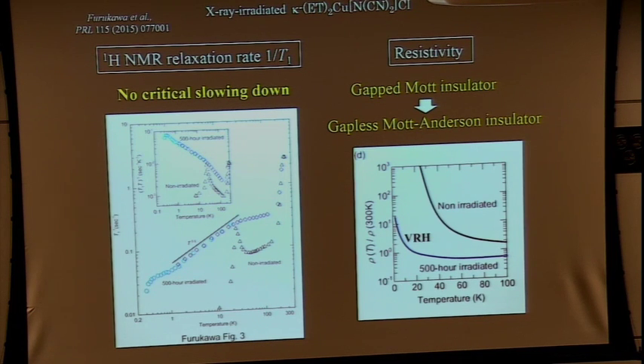However, we have to pay attention to the charge degrees of freedom. This is an insulator. However, after the X-ray irradiation, the temperature dependence of the resistivity changes from gapped behavior to gapless behavior. This temperature dependence is very weak, still insulating, and is well reproduced by variable range hopping. This means it's insulating, but a very disordered insulating state. So this state is regarded as a Mott-Anderson insulator: a Mott insulator, but with very serious disorder introduced. In such a case, the gap is collapsed, and in this very disordered Mott-Anderson insulator, the interaction and disorder play similar roles in localizing electrons.